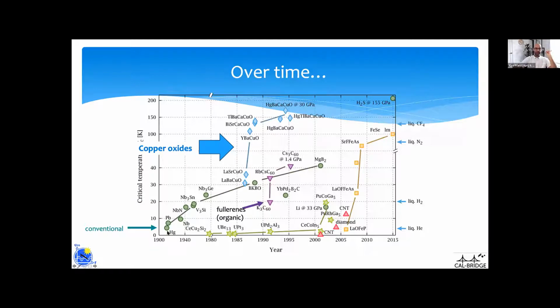Over time, I'm plotting here the year versus the transition temperature of certain materials. You have a bunch of materials, and you're seeing the year they were discovered to be superconductors and the critical temperature of those materials. You can see that the very first superconductor discovered was mercury, in 1911, as I showed you. Then over time, people have found other materials, and the transition temperature TC keeps rising. But the limit of this conventional theory says that all materials should be around this level right here, 40 Kelvin.